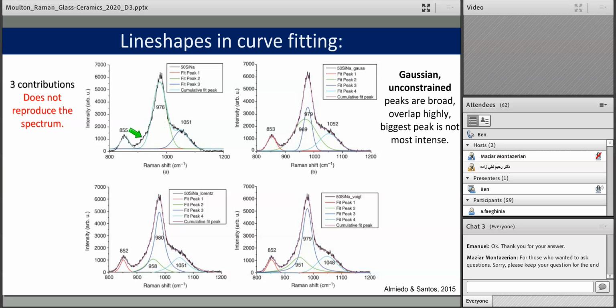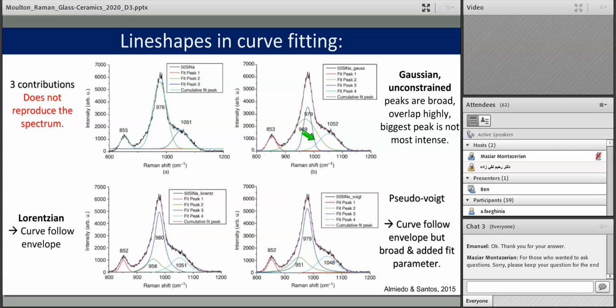If you add another peak to fill these gaps, for instance, but leave it totally unconstrained, you'll get the fit here. And the sum of these peaks really well reproduces the spectral envelope, so the peaks and valleys here. But you'll see that there are high degrees of overlap, and you have peaks with very similar centers but very different shapes. This one is quite broad, this one is quite skinny. All of these overlap in this region here. For me, this is too much overlap. We don't see this type of behavior in crystals, so I would consider this a very poor fit as well.